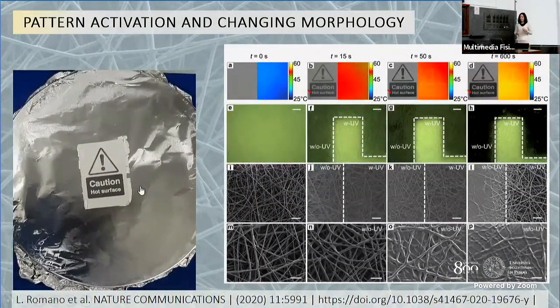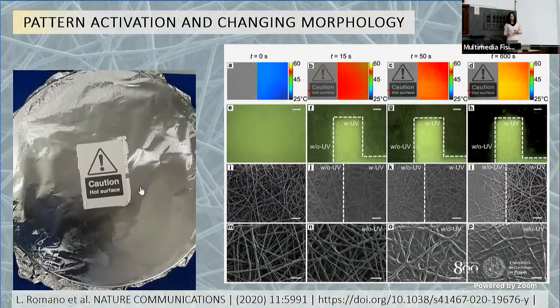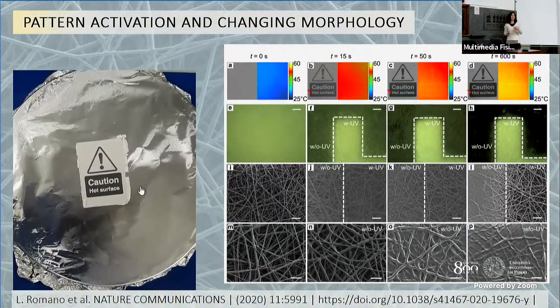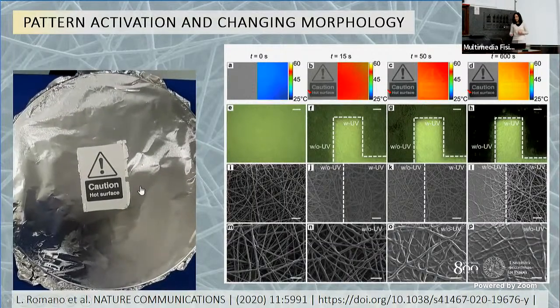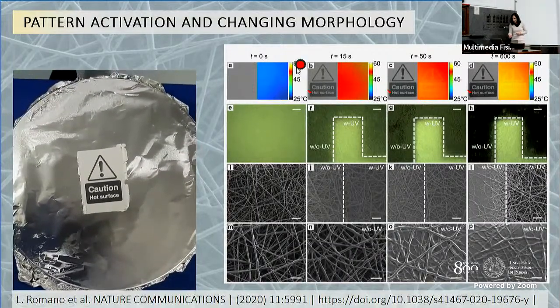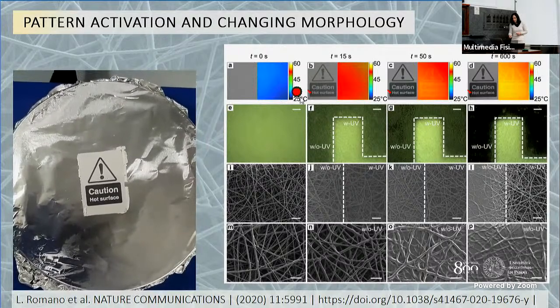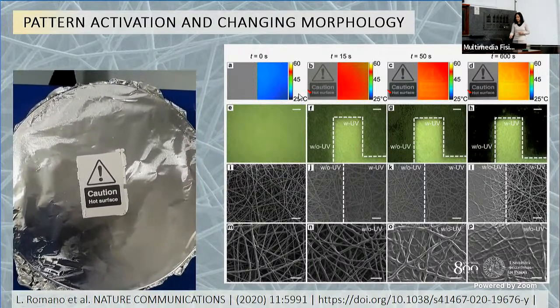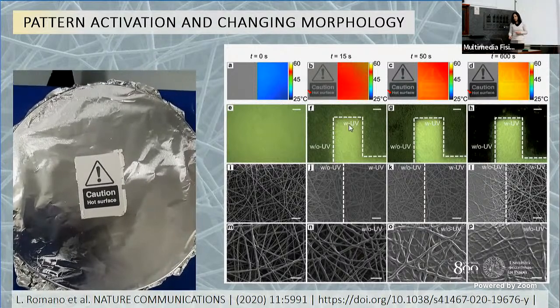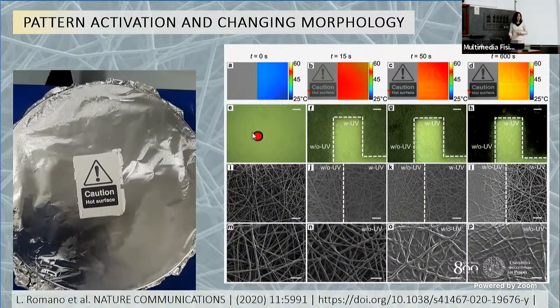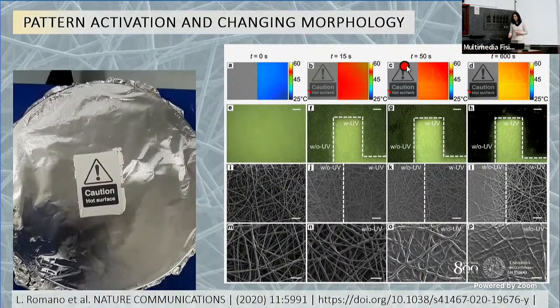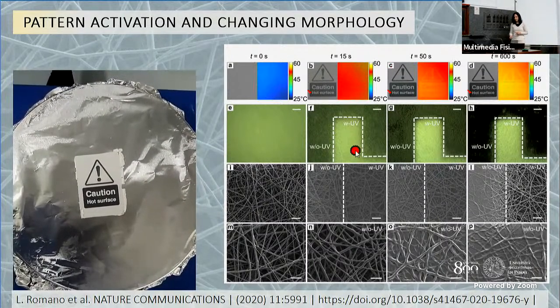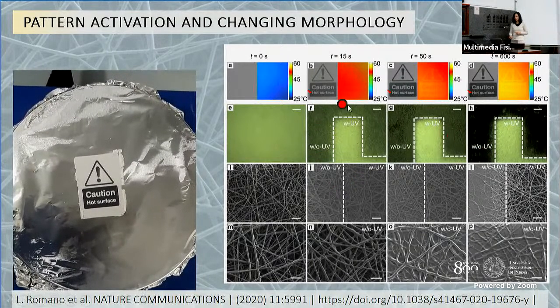Just for curiosity, I want to show you at the microscopic scale, by SEM, what you can see in an interval around this H letter of hot, okay? So this is the H. And you see that at the beginning, you have just fibers on the surface, and you cannot see any letter. But then when you increase the heating time, you see that these H letters appear and it is always clearer.